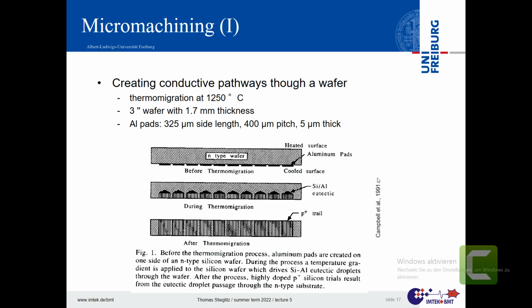They took a piece of silicon called a wafer, and now the task is to make a conductor between the back part and the front part without short-circuiting adjacent areas. What has been done in those days, going back to the late 1980s, early 1990s, was to put aluminum on the back side and then have a strong temperature gradient between front side and back side. If you look into material science, we have a eutectic alloy between silicon and aluminum. That means the melting point of that alloy is lower than the melting point of aluminum and lower than the melting point of silicon. That's the definition of a eutectic.